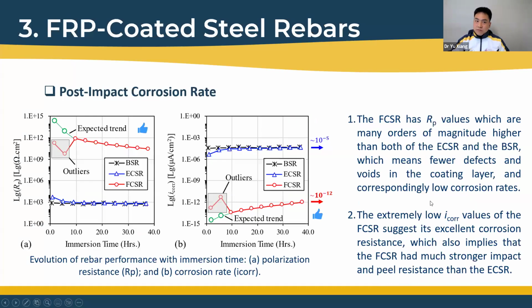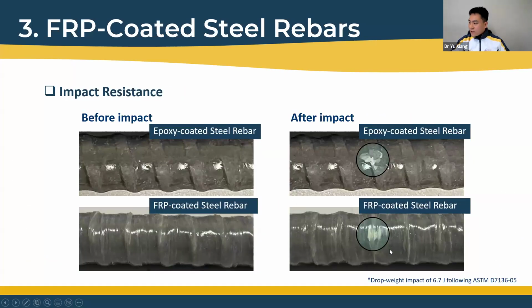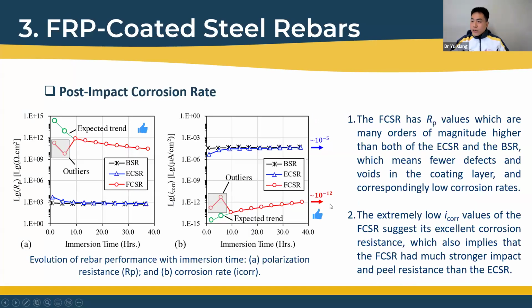To prove that the deeper layers of the FRP coating remain intact, we immersed the impact-damaged specimen in sodium chloride solution and measured the corrosion rate up to 36 hours. We call this the post-impact corrosion rate, because if the coating layer has been damaged, the corrosion rate will be very high, reflecting the state of the substrate steel.